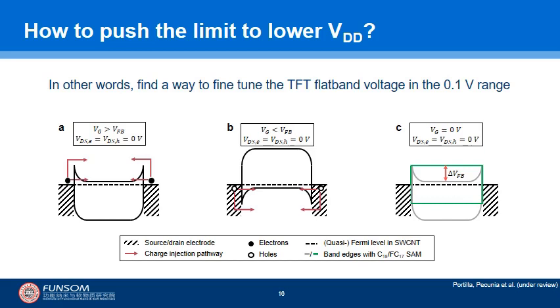But if we could somehow shift the flatband voltage by an amount in the 0.1 volt range, at Vg equals 0 volts, the energy bands of the semiconductor would look like the ones shown in green, and the TFT characteristics would then be centered around 0 volts as desired.